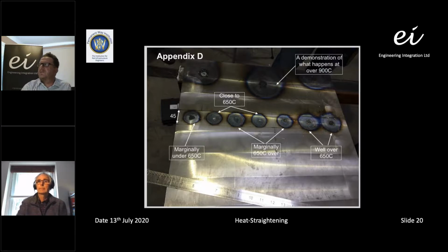So if we've got a crayon that's defined to have a 650 degrees C category, we apply the stick on the center of the heating pattern, and if it melts, it's above 650 degrees C. If it's lower than that, it's obviously below.